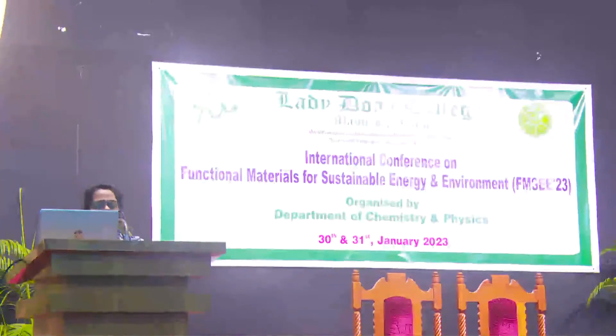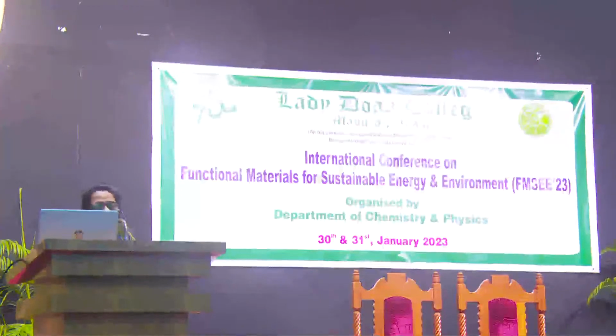Yes. Mostly for kesterite-based solar cells, CZTS is widely used, for which the efficiency is 12%. But even though decades of research have gone into CZTS, the major three problems could not be rectified, that is, the binary phase defect, the anti-site defect, and the band tailing. Here, the anti-site defect could be reduced by copper barium tin sulfide. Here, zinc is replaced by barium, which has a different ionic radius.